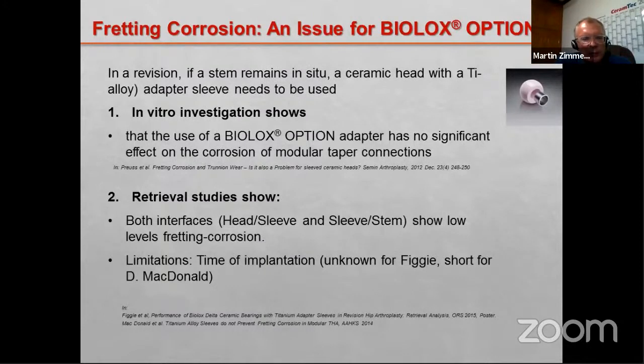With up to 10 million cycles, there was no occurrence of fretting or corrosion, thanks to the fact that the sleeves were made of titanium aluminum vanadium alloy.